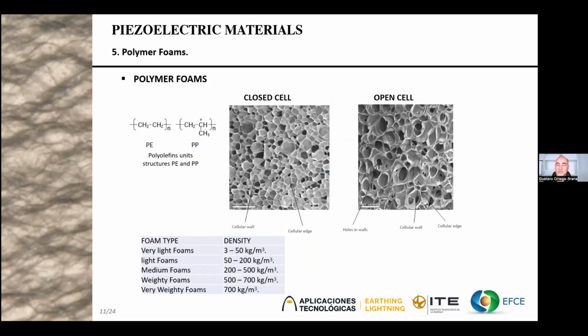Our work was based on a closed cell polymer foam that belongs to the polyolefin family. We can find this polymer commercially and it is inexpensive. There are several densities that depend on the application. We can see in the picture a closed cell and an open cell. That property depends on the fabrication, and for our necessities we need the closed cell polymer, because we need to generate a macro dipole inside of the voids with air.